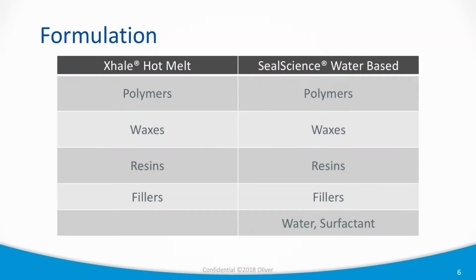Types of adhesives, the hot melt adhesives and the water-based adhesives, and there's a lot of commonality in the formulations, really. We start with the base polymers, which are typically ethylene vinyl acetate copolymers. We do use other polymers for specialty applications, but the basic hot melts are EVA polymers. We use waxes, and that's largely to control this peel strength, adjust the cohesive strength of the adhesive. Waxes also serve to help with anti-blocking. That's so you can coat and roll the coating up on itself without it sticking to itself.